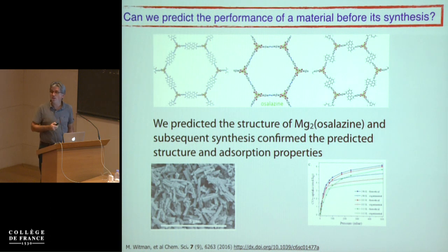And what you can already see, there are databases of, say, 30 million known chemical structures. So what you need to do is filter those databases for approximately the right geometry, so that those OH groups are at the right size. And then you can see whether you can synthesize this material. So we predicted this one, and then subsequently in my group, they synthesized the material.